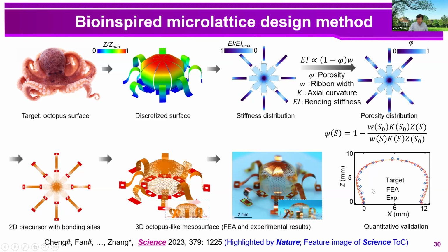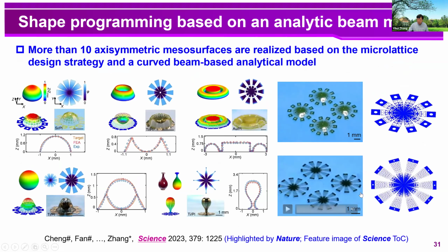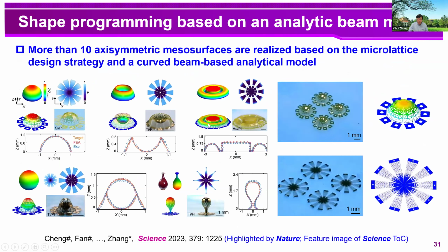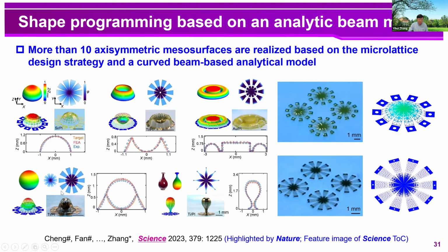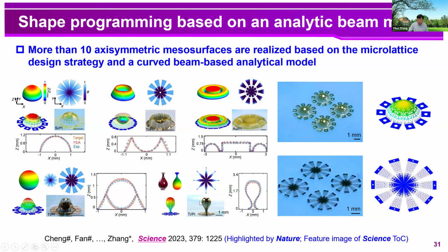So according to the comparison here, the profile of the octopus pad shows very good agreements between our experiments and our design target. So based on this inverse design method, we have achieved the inverse design of more than 10 axisymmetric meso surfaces, with a few examples shown on this slide, including, for example, the hemisphere, this kind of volcano-like surface, and this palace-like surface, as well as an entire sphere, the vase-like surface.